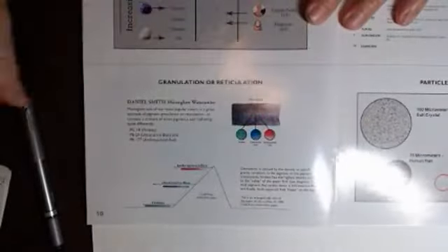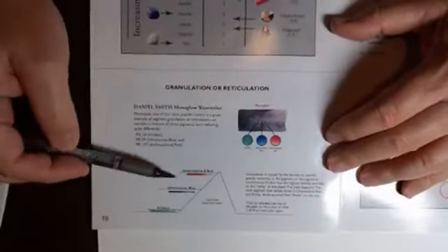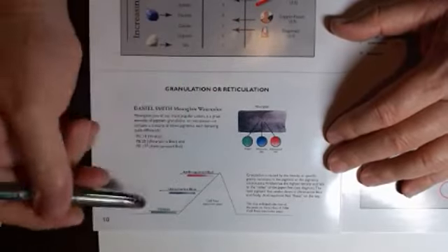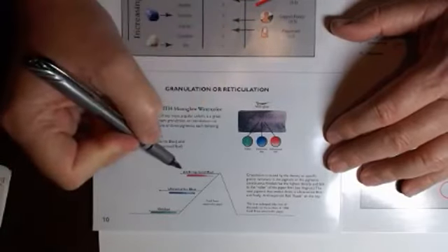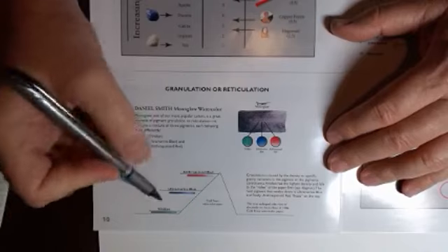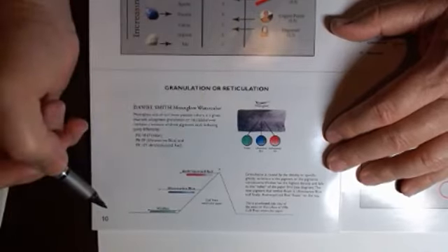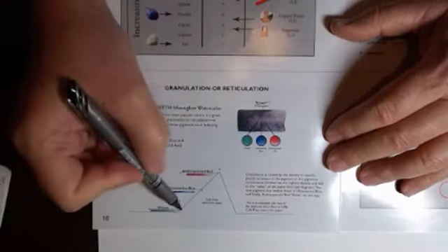And then we go over granulation. This is the thing that we've been talking about quite a bit, granulation. Granulation is caused by differential specific gravity, and where the particle goes on paper, for example. If we looked at this, which is Moon Glow, which is made up of the anthraquinoid red, the ultramarine, and the viridian, the anthraquinoid red is very, very light, and it stays at the very top of the mountain. The ultramarine, a little bit heavier, stays in the middle, and the viridian goes to the bottom. That's what gives us our granulation of the Moon Glow.